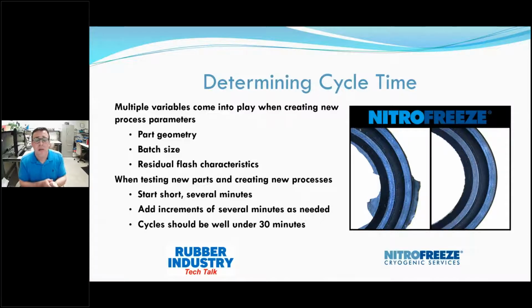So what we always recommend when we're creating a new process is to start short. You don't want to go and say, yeah, let's do this for 15 minutes, because you can always run it for a couple minutes and then add a couple minutes and do it in small increments. You don't want to just dive in and say, yeah, let's do it in 5 minute intervals. The idea is to start with a short cycle, a couple minutes, and add the additional minutes as you go. So you run the parts, pull them out, take a look.